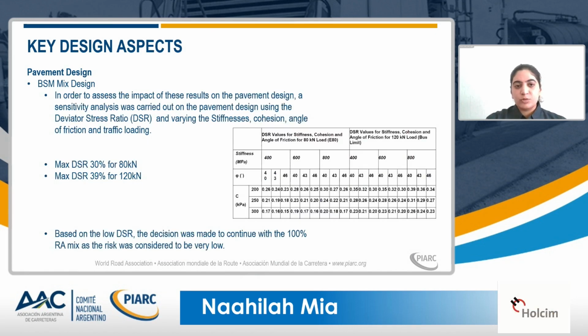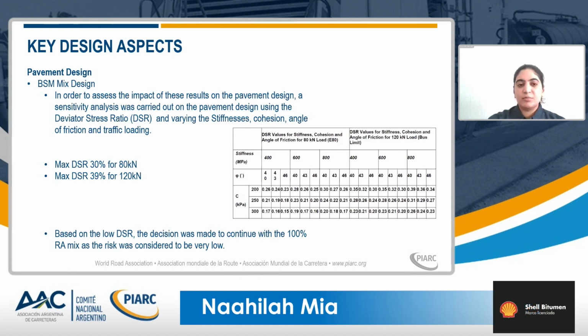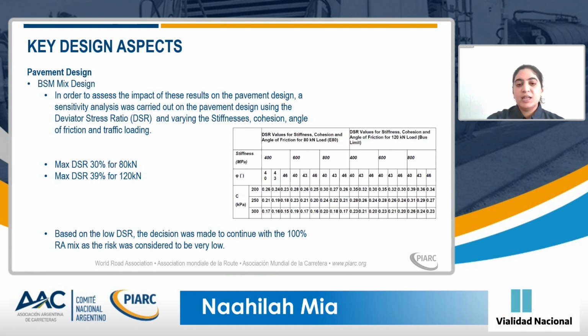So as part of the BSM design, in order to assess the impact of not meeting the specification, a sensitivity analysis was carried out on the pavement design using the deviator stress ratio, the DSR, varying the stiffness, cohesion, angle of friction, and the traffic loading. As you can see from the results on the right-hand side, the DSR was 30% for the lower load and the maximum DSR was 39% for 120 kilonewton. Based on the low DSR values that we saw, the decision was made to continue with the 100% RA mix, as the risk was considered to be very low.